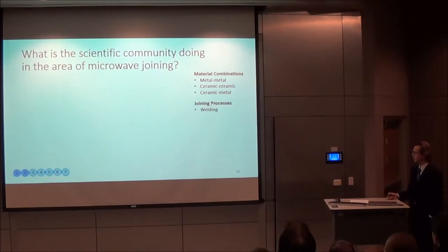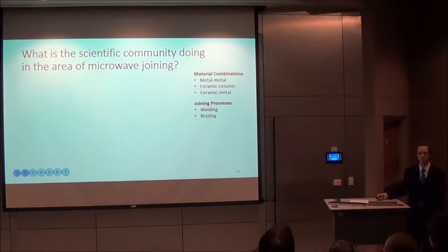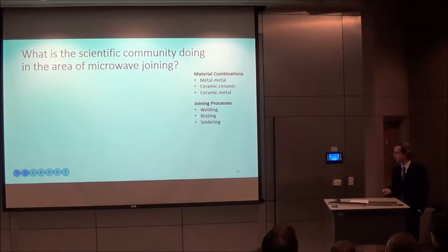Different joining processes are used where we're directly welding the base materials or brazing them using some interlayer that will melt and bond the two. Soldering, which is just a lower temperature than brazing, above or below 450 degrees Celsius. And cladding, where you have a metal that's applied on top of another to give it corrosion resistance.